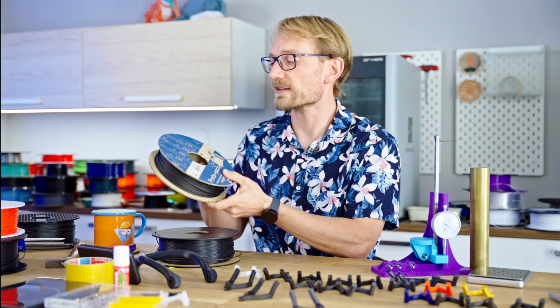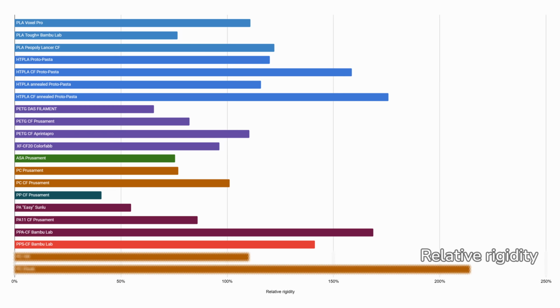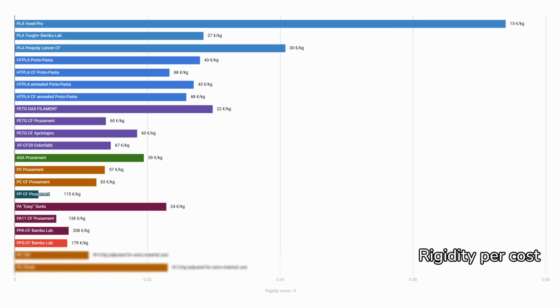And that opens up a different way of looking at these results, because yes, some of these filaments are more rigid than others, but there is a much, much bigger gap in how much you pay for the filament itself. And once I rank them for rigidity per cost, then the entire thing flips around. With PLA, plain old, non-tough, just non-reinforced, just basic PLA, being more than twice as good as most of the other filaments in how rigid of a part you get versus how much you pay for it. In general, the more high-end a filament is, the less value for money you are getting.